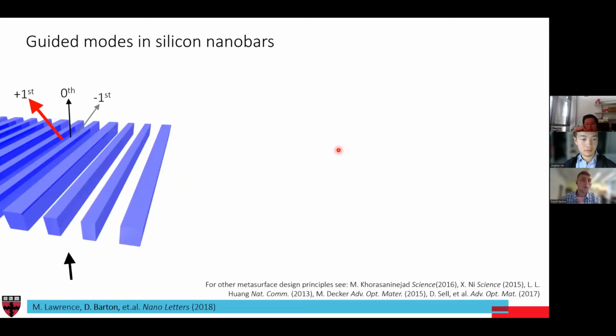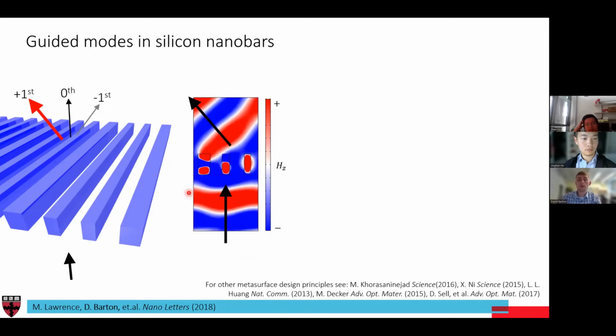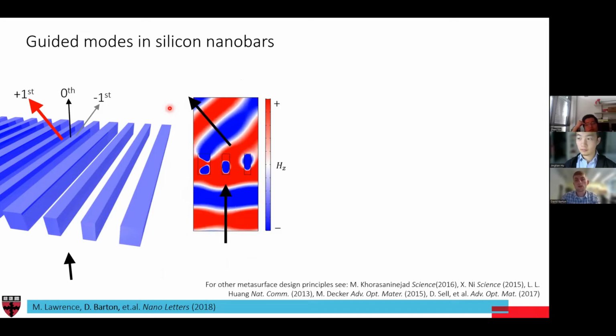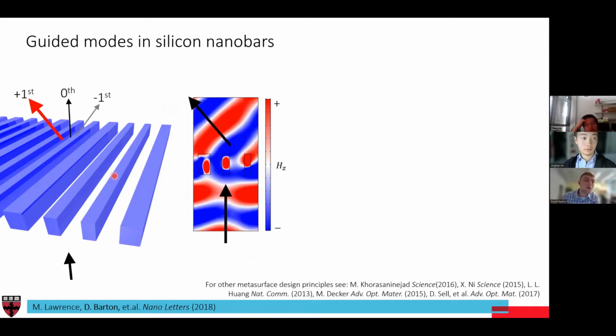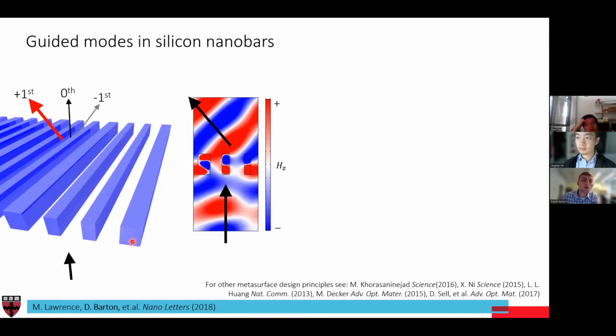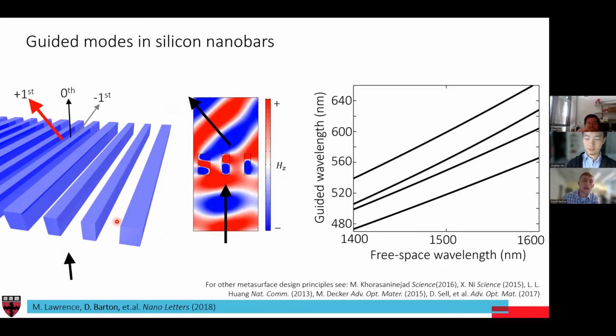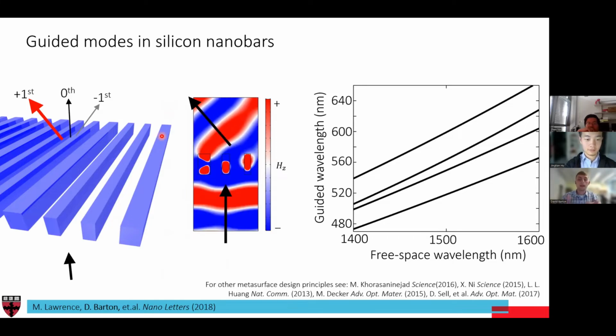And the way we do that is using the same design that I showed earlier. We have these arrays of bars. If we do a full simulation, we have light coming in from the bottom, and we can redirect it to a particular direction, in this case about 45 degrees. This is a standard way of designing things, but we also know that this structure is a bar of material that has a higher refractive index than its surroundings. What this means is that it has a whole spectrum of guided modes that propagate along this bar and can be trapped in the same way that an optical fiber does. It can guide light in very particular ways.